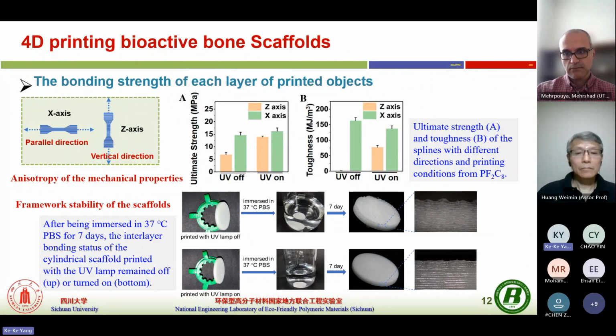We also tested the framework stability of the scaffold by putting it in PBS solution. We found that the printed object with UV irradiation showed much better stability in the water environment.